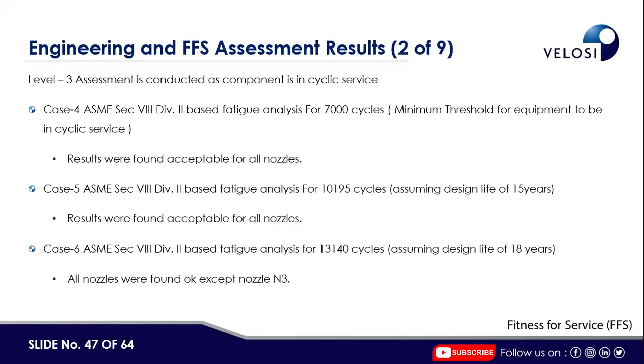Level 3 assessment is considered as the component is in cyclic service. Case 4, ASME Section 8 Division 2 based fatigue analysis for 7,000 cycles, the minimum threshold for the equipment to be in cyclic service. Results were found acceptable for all nozzles. Case 5, ASME Section 8 Division 2 based fatigue analysis for 10,195 cycles, assuming a design life of 15 years. Results were found acceptable for all nozzles. Case 6, ASME Division 2 based fatigue analysis with 13,140 cycles, assuming a design life of 18 years. All nozzles were found okay except nozzle N3. It means that was the limit, and nozzle 3 was identified as a limiting component.